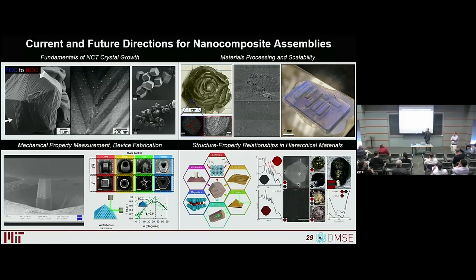We take a tube with all the sample in it. We put it at a high temperature and then slowly cool it down. That's all. There's no stirring, no mixing, no addition of anything. It's just a slow cooling process. What is different is that if we cool more slowly, we get the stellated dendritic growth. If the concentration is higher, we get more hexapodal or dendritic growth. Or if the particle to polymer ratio is skewed. So if we have a smaller particle with a softer polymer corona, that skews towards hexapodal growth. All those variables push it more towards hexapodal growth.